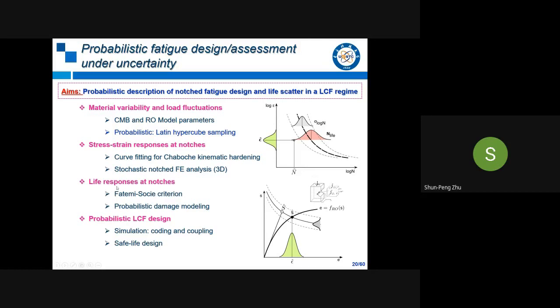And the third step, we try to quantify the life response at the notches. Here we choose the Fatemi-Socie criterion, which is commonly used for notches in multi-axial fatigue analysis. Then we model the probabilistic damage, and use this to locate the code or the procedure for the fatigue design.